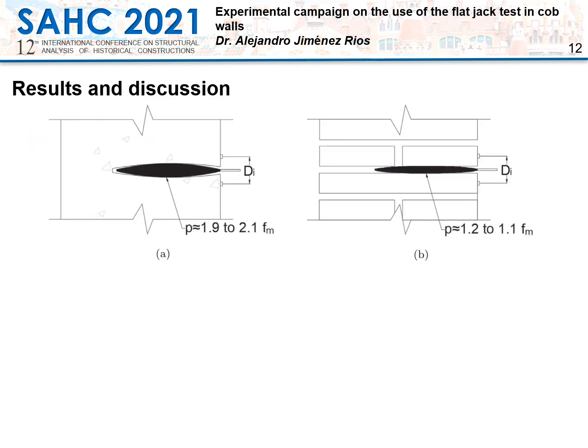A detailed study on the distribution of the stresses induced by the flat jack on the fabric, performed by Hughes and Picard, showed that the pressure was indeed higher at the center of the flat jack than at its edges. This phenomenon is amplified in cob walls, and therefore the value obtained for the dimensionless coefficient Ke is smaller than the values of Ke for other wall typologies, for example 0.9 for adobe walls and 0.82 for rammed earth walls, as reported by Lumbillo. This can be justified by the fact that cob is relatively weak and flexible in comparison with other materials, namely adobe or rammed earth, as shown by Micoli et al., and stone or brick masonry, as shown by other authors. As a consequence, when the pressure in the flat jack is increased, it deforms more like a balloon than like two parallel plates being perpendicularly separated.